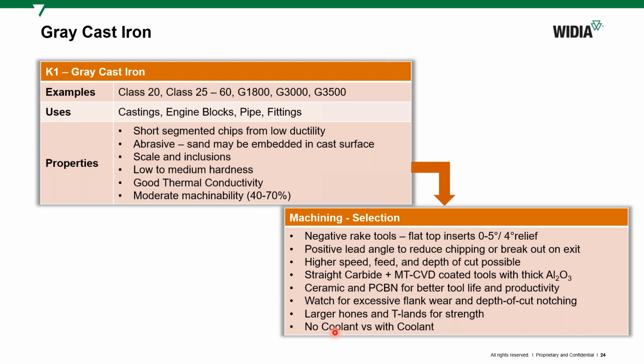But for the last few years, we see that cast irons are also machined at very high cutting speed. With carbide, we go up to 600 meters per minute. So much heat is generated that it has to be taken care of. Otherwise, the component will get disturbed, and the tool will also wear out faster. The coolant will help to take away that heat. If you're running at lower cutting speed, you don't need a coolant. But if you're running at high cutting speed, coolant is preferred.